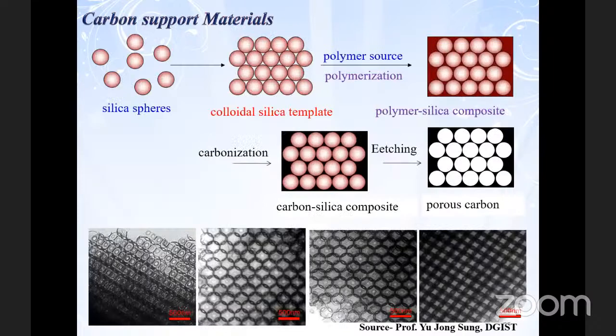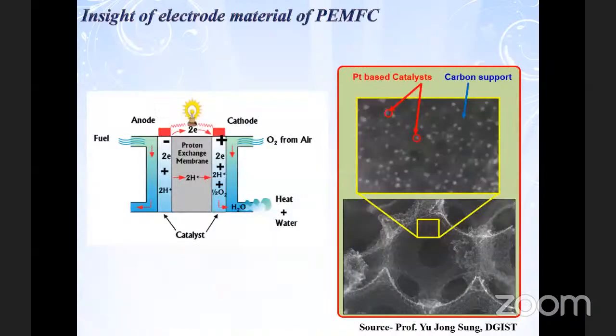Okay, so the synthesis of carbon material is a very lengthy process. First, you prepare the silica, and then you fill the polymer sources, and carbonize it, and then remove the silica or whatever the template material. We say this is the template method. First, you have to synthesize the template, fill the carbon, and carbonize it. It means heat it at a higher temperature and remove the template material, which is silica. Then you get the highly porous carbon material, and in the next step you deposit the platinum catalyst on that. So this is a very lengthy and long process.